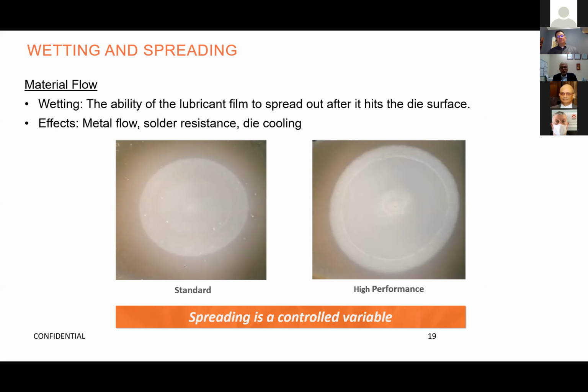And here again, we can look at any one of these properties. We can focus just on cooling, so I could provide a die lubricant that gives the best cooling you ever saw and the highest die adhesion. But it might also give you the worst buildup you ever saw in your die, which leads to plugged vents and porosity and everything bad that goes along with it. So it's really about we choose our components purposefully in order to get the right balance for a product and for a process.